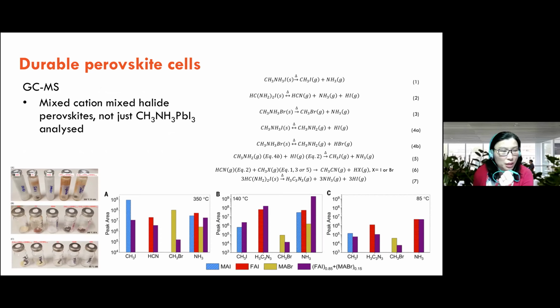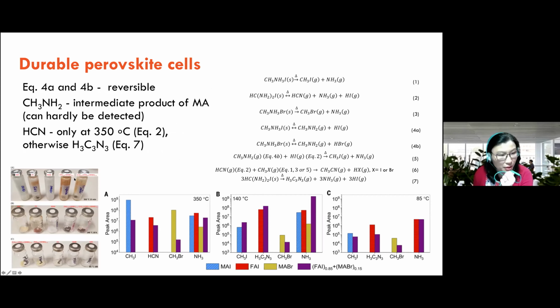So what we do is we heat up the precursors. We heat up the MAI, FAI, MABr, and the mixture of the precursors at 350 degrees, 140 degrees, and 85 degrees for different times. At high temperature, we don't heat it as much because they don't operate at 350 degrees in the field. At 85 degrees, we heat it for 100 hours because that's the likely temperature they will operate at in the field, even though they don't go for 100 hours, but why not? We're going to torture it anyway. So let's see what happens.